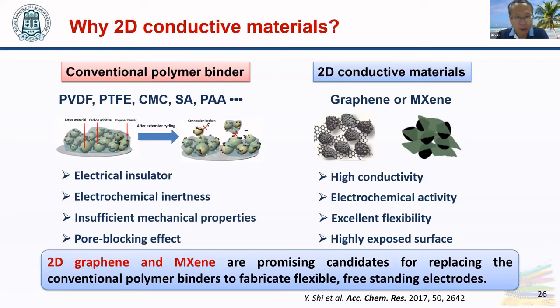The electrode fabricated by polymer binder has insufficient mechanical properties, so it cannot meet the requirements of flexible devices. Sometimes we worry the polymer binder will block the pores of porous carbons. Although polymer binder has so many shortcomings, replacing it is not an easy thing. It is a challenge.